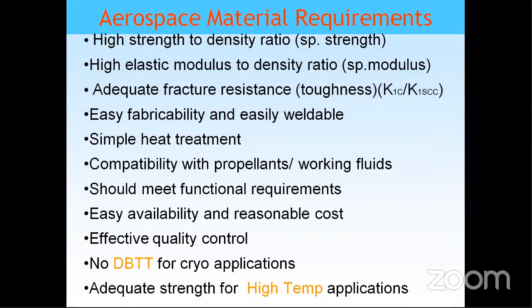Then we have adequate fracture resistance. Everything is giving margin, but except for K1 SCC. The K1 SCC is nothing but fracture toughness in stress corrosion conditions. Actually, stress corrosion resistance of maraging steel is very, very poor. Then easy fabricability and easily weldable. Good, that is very, very important, because I can make a lot of alloys. If fabrication is difficult and it's not weldable, it's a problem.